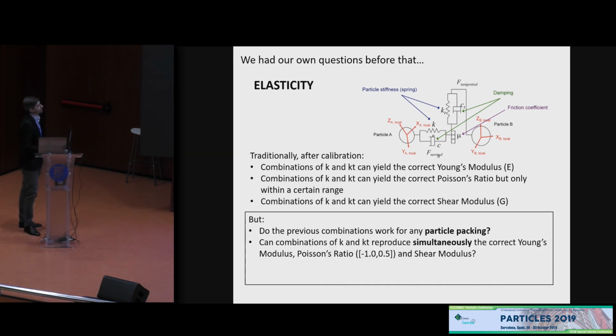And those combinations of normal stiffness and tangential stiffness can reproduce simultaneously the correct Young's modulus, Poisson's ratio, and shear modulus. I mean in different tests. So you do one test for Young's modulus and check it, and with the same calibration, you try a different test to measure the shear modulus. Does that work? And the answer, in our opinion, is no.